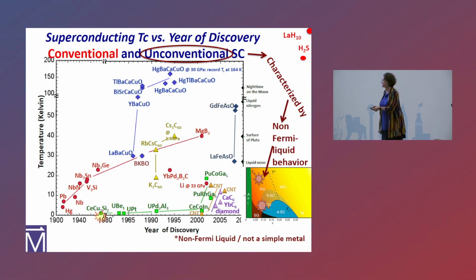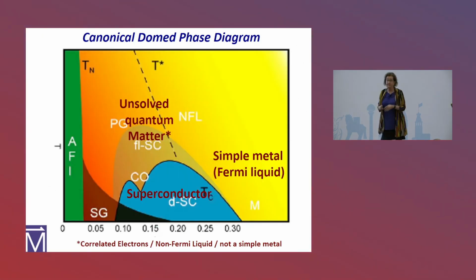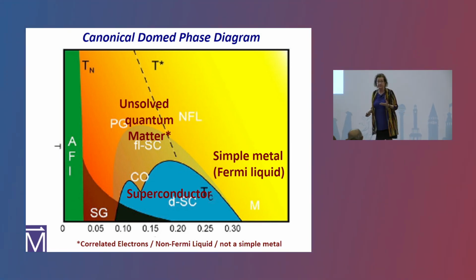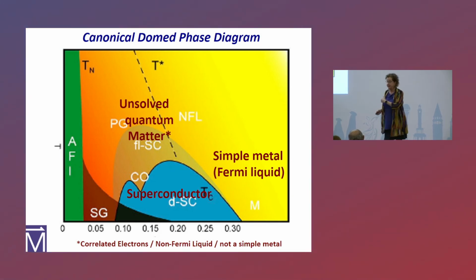And I think I blew it up on the next one. Yeah, so here I've blown this up. The y-axis is temperature. The x-axis is a thermodynamic variable, typically pressure or doping. You can use magnetic field in some cases. But in any case, on the low pressure, ambient pressure, low doping side of the phase diagram, you typically have an antiferromagnetic insulator. Over on the right-hand side, you typically have a Fermi liquid.